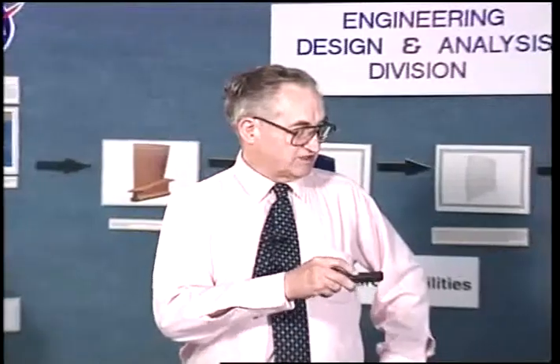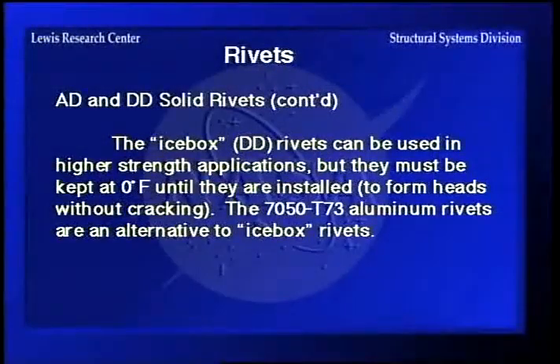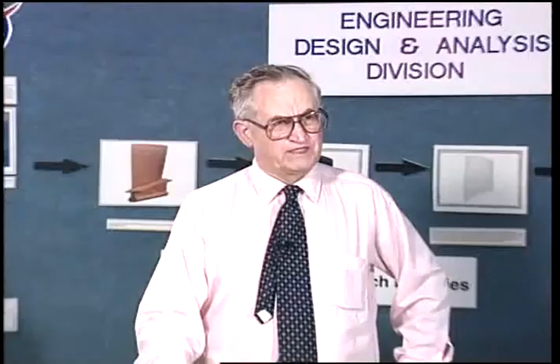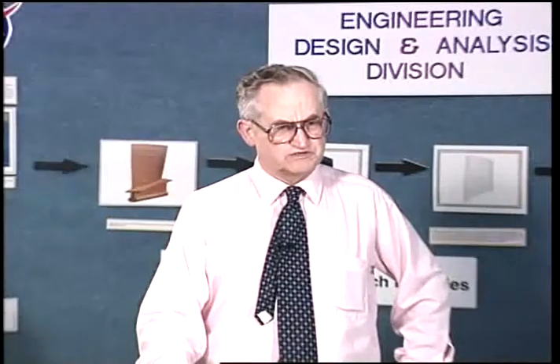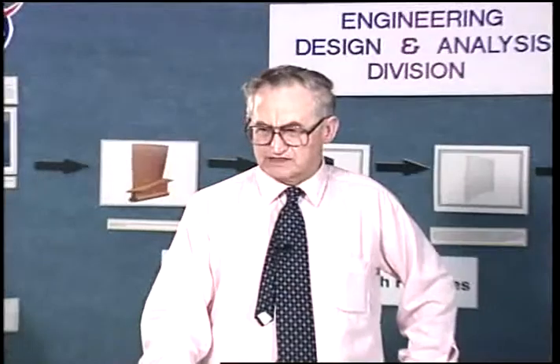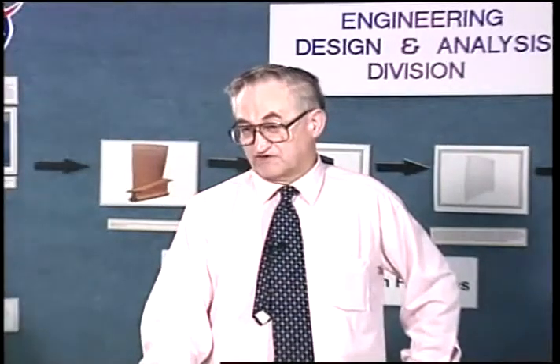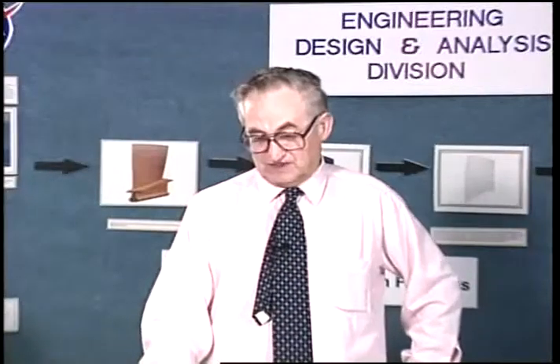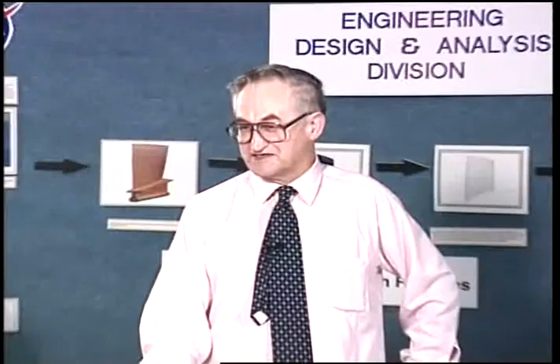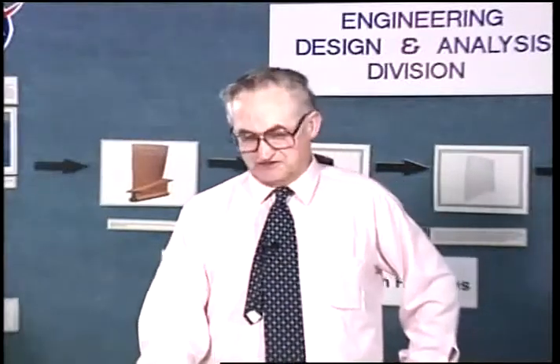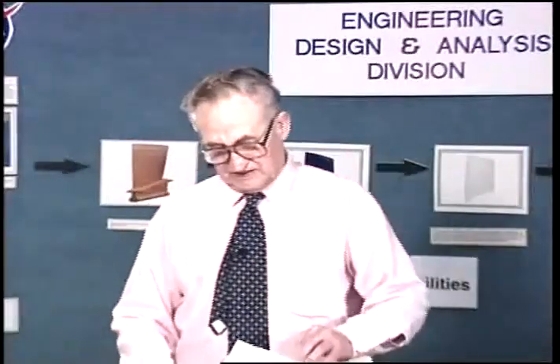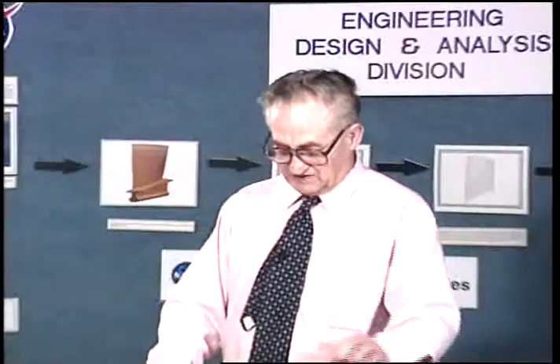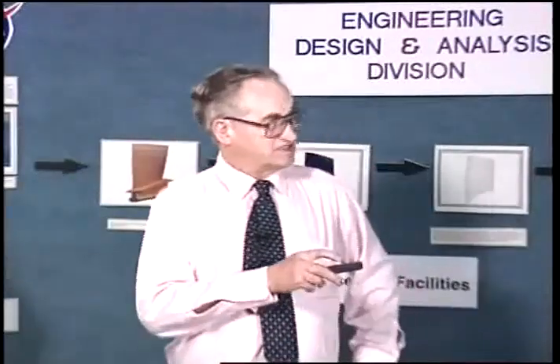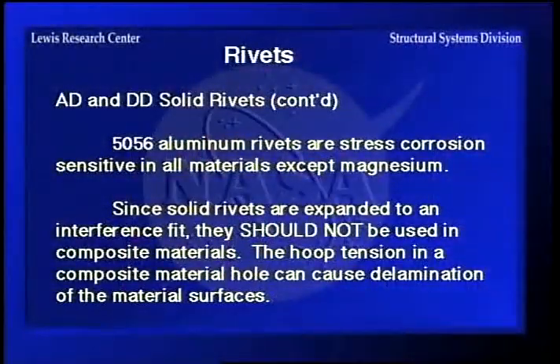The icebox rivets I mentioned earlier have to be installed at 0 degrees, which makes them not very popular. The other thing you run into: if you don't use a batch of them, you have to take them back. If they've been exposed to room temperature for very long, you have to take them back and reheat treat them, and then cool them down again before you can use them. Sometimes they've had trouble with people shortcutting things, saying, oh, they weren't out that long, so we'll just go ahead and reuse them, and then they get rivet cracking. So they're very hard to control to make sure that you get a good heading operation on them. The 5056 I mentioned is stress corrosion sensitive in all materials except magnesium.